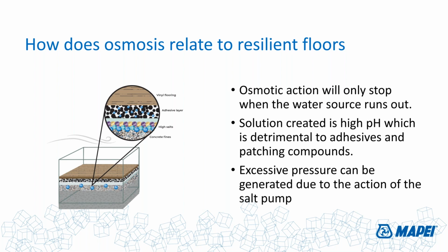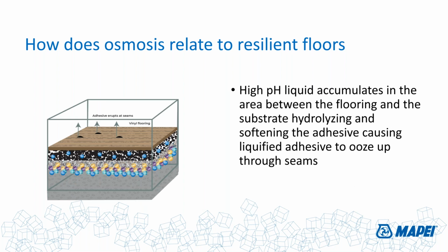That salt pump generation of liquid is a solution full of calcium hydroxide, sulfates, and all sorts of stuff that are going to be detrimental to the adhesives, patching compounds, and in some respects even the flooring material. This is a big problem, and this is, in my opinion, what's happening when you pull up a piece of sheet vinyl and you see soup under the floor. My hypothesis is 9 times out of 10 that was the direct result of a salted slab that had a high concentration of some sort of salt contaminant on the surface of it, creating an osmotic action, the salt pump sucking liquid up out of the concrete slab, creating this high pH solution, dissolving the adhesive, hydrolyzing everything, creating a massive problem for us. Again, that's what we're talking about here, the high pH liquid.